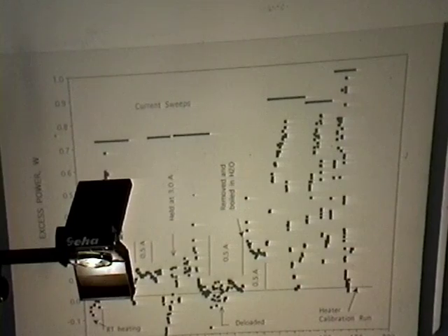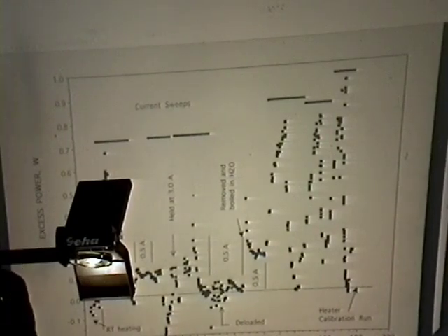So obviously there's something going on at the surface that is interfering, and you can remove it by just allowing it to dissolve off if it's not too thick. But if it builds up too thickly because of the current being too high, you have to take it off by more robust means. After having boiled it, you can see I was getting excess heat, and then I did this study. There are 3 sweeps done in a row. They were done taking a different number of data points. Now, I should go back and explain what one of the explanations was.